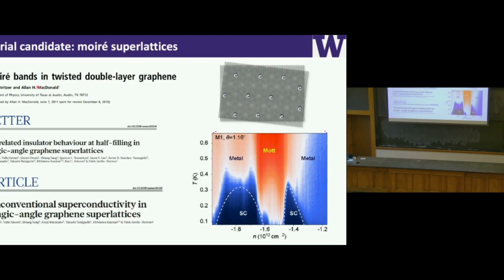But I think the breakthrough really comes from two works. The first one is the theoretical work by Allan MacDonald, which shows that there is a magic angle in twisted bilayer graphene, which shows flat bands. The second, I think, that really motivated the field is the work from Pablo at MIT. They observed unconventional superconductivity in magic angle graphene. So that really shows that once you have these moiré materials, we have an opportunity to engineer flat bands.